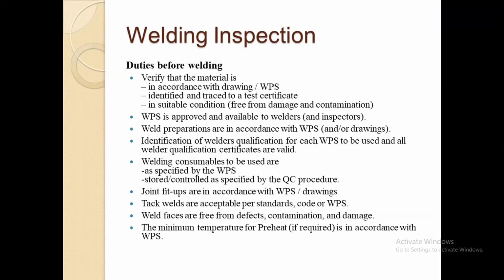properly. The inspector has to check the joint fit-ups, that they are in accordance with the WPS and the project drawings, to make sure the tack welds are acceptable and up to standard, and that the weld faces are free from defects, contamination, and any damage. The inspector also has to make sure that where it is required, the preheat temperature and also the interpass temperatures are maintained within the required regions.